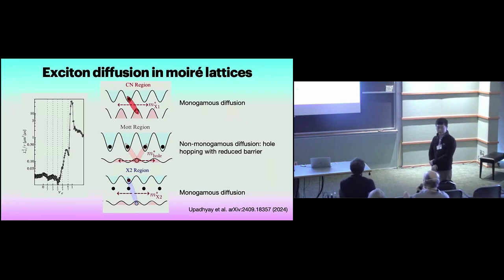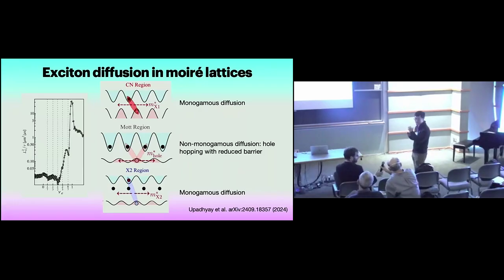So how do you reconcile this observation with the observation a few slides ago that the diffusion is suppressed? Oh, that's a great question. In that experiment, we are using a very high pumping power. So we are feeding the excitons, almost one exciton per Moiré unit cell. Here, the key observation was actually, we didn't intentionally try to do this. We were very interested in the low power regime. So we go to the low power regime where there are very few excitons in the Moiré cell. So it's mainly the electron interacting with the exciton.